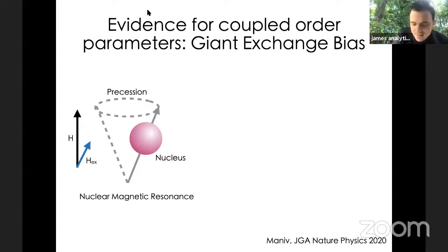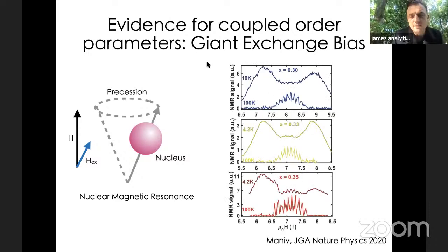Yeah. We've done some nuclear magnetic resonance experiments to try and see what the local environment of the spins actually was. And from all of these experiments, so you apply magnetic field, you look at the precession of the nuclear moment, and that can tell you what the local environment is on average. What we found, so here is what the NMR signal looks like as a function of magnetic field. Oh, by the way, done in the high field lab in Tallahassee. What we found at high temperatures, these peaks that you see are actually connected with the nuclear moment of the niobium, so the niobium 9/2 moment.